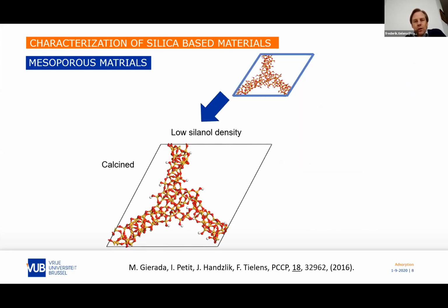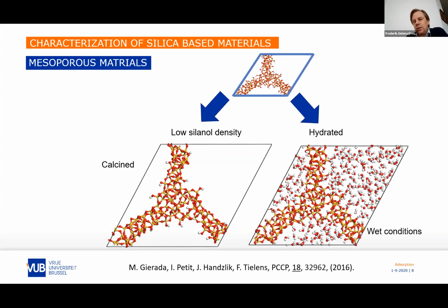From this structure, we could start to analyze the effect of hydration in these kinds of materials. Most of the time, if you do catalysis, you calcine the structure, so you dehydrate strongly. This means that the structure here also changes, because the silanols, which are there due to the interaction with water, leave the structure and form a siloxane bridge. So there is a kind of dynamic process at the surface. The opposite occurs when you hydrate the surface completely, so you go to a maximum of silanols at the surface.